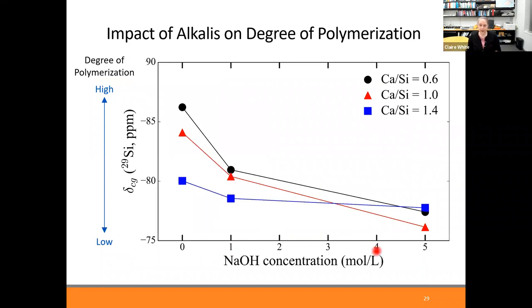So on the x-axis, the gels were synthesized using various concentrations of sodium hydroxide. We synthesized gels with varying ratios of calcium to silicon, and we're plotting the center of gravity from the NMR results versus sodium hydroxide concentration that was used for synthesis. And what you can see is this center of gravity decreases for all of the different compositions, which is showing you're going from a high degree of polymerization when there's no sodium to a lower degree of polymerization when there's more sodium. So what this means is you're getting shorter chains of the silicate units when sodium is present, which could make the structure more prone to degradation, which is not a good thing.